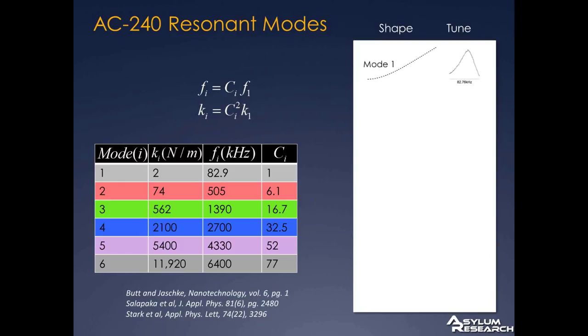So if we look at the first mode, it looks like this. The shape is up like this. It bends, looking a little bit just like a deflecting cantilever. You can see here is a tune, centered around 82 kilohertz. The second mode, here at 505 kilohertz, is shaped like this. It has a node here in the center, basically where the cantilever is not moving.